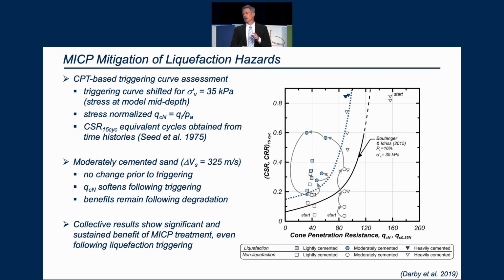The series of gray arrows shows you essentially the walk, if you will, of the moderately cemented material. And you can see going up from the middle and the bottom upwards, those series of open symbols are all cases where this material and this model did not liquefy. And it's only at that very large shaking event, where the cone tip resistance shifts to the left a little bit, do you start seeing liquefaction. And you have another liquefaction event slightly above that one. And then we dropped the loading level down to the very small levels and repeated the process.